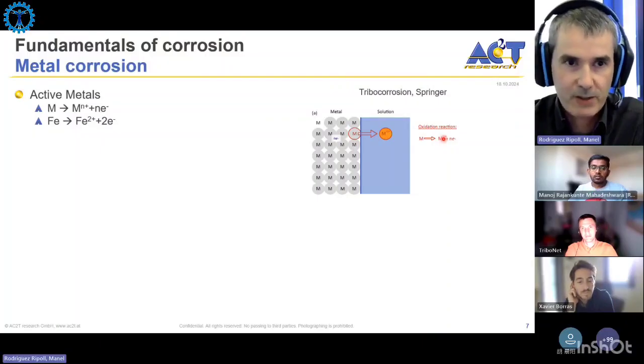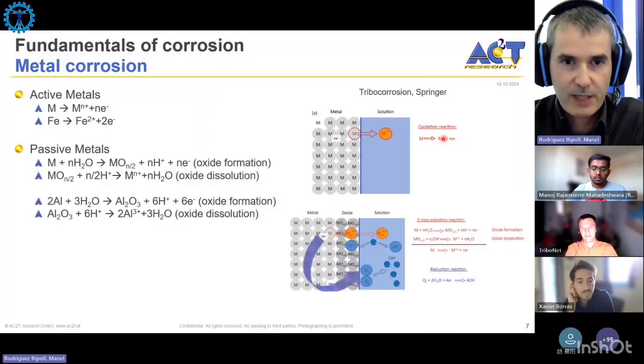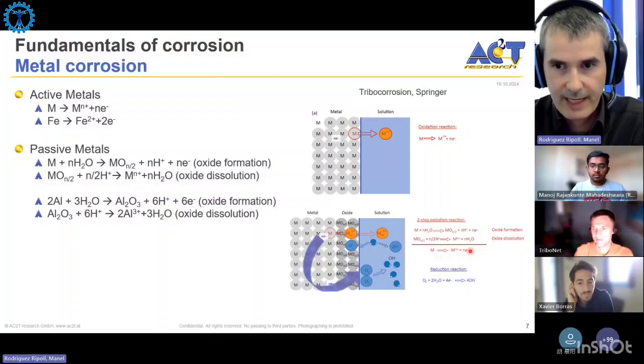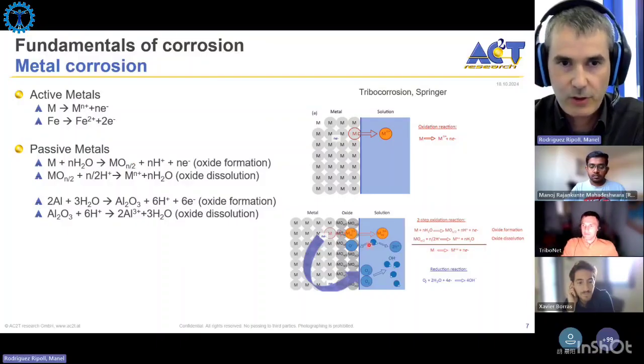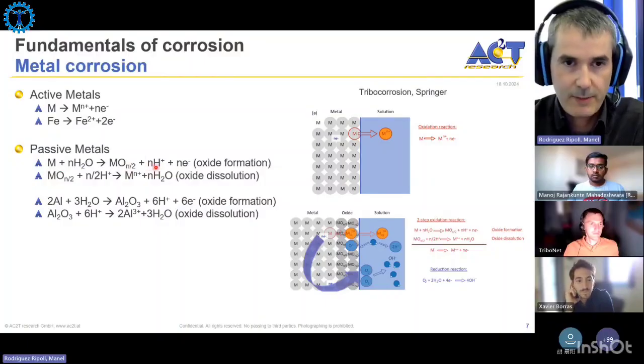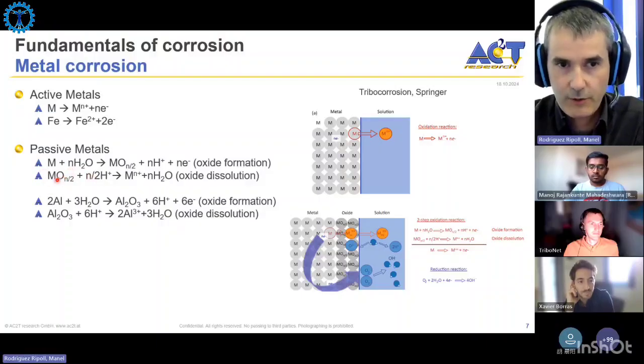However, other metals build up a spontaneous passive layer. So basically the process, if you make the sum, is the same. A metal ends up having a dissolved metal, an ion, and some electrons. But this is done in two different steps. The first step is an oxide formation. You have the metal reacting with water and forming an oxide layer with the emission of some protons and some electrons. And then in the next step, this metal oxide can dissolve, react with the protons, and end up dissolving and having water again.